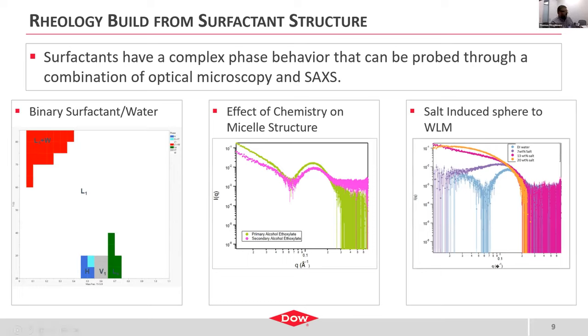However, we know that it's not as simple as this when you're in this dilute micelle regime. Not everything is this nice spherical micelle like I showed on the last slide. By changing the chemistry of the surfactant, you can see how the structure of the surfactant changes. What's shown here in the middle is a comparison between a primary and secondary alcohol ethoxylate. So what you're doing here is you have a long-chain hydrocarbon covalently bound to a polyethylene glycol block, and you're changing where that bonding happens.